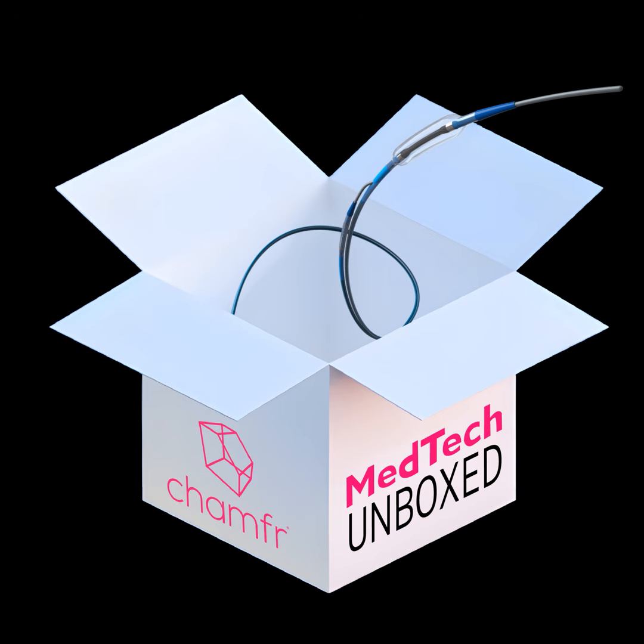But now you have some other, let's say neuro product, that you want to have a very soft distal end, but you still want to maintain some kind of rigidity in the proximal. In this case, I think this is where thermoplastic liners shine, because you can weld them together. You can connect different sections. So now not only the PEBAX jacket has the ability to vary durometer. Now, if your liner can also vary durometer, then I can have a standard catheter all the way to the last, let's say, 10 centimeters, and I can transition to a softer liner.